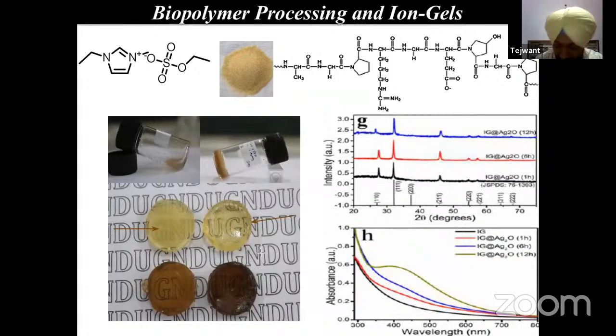So what can we do for making this gel stable? We have prepared silver oxide nanoparticles in situ inside the gel. The preparation of silver oxide nanoparticles has been characterized by a variety of techniques, and the gels shown in the lower panel are the ionogels, meaning having ionic liquid. One is ionic liquid, second is gelatin, and third one is silver oxide nanoparticles. The silver oxide nanoparticles are very good antimicrobial agents.